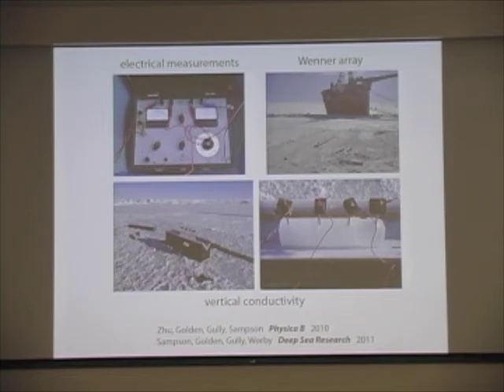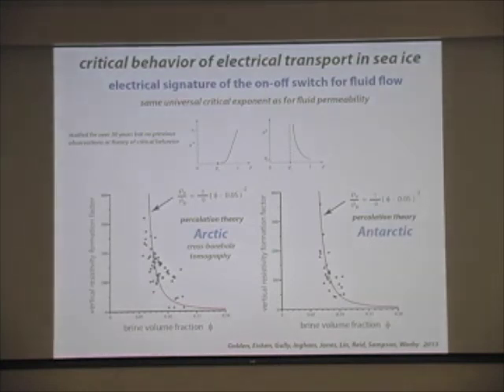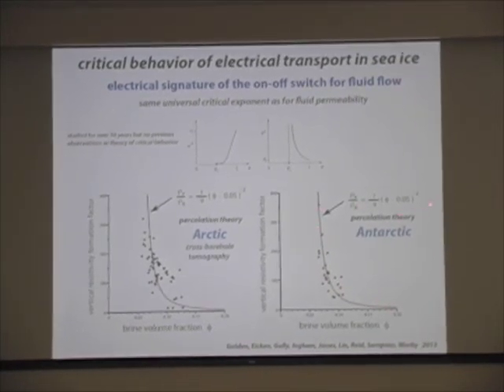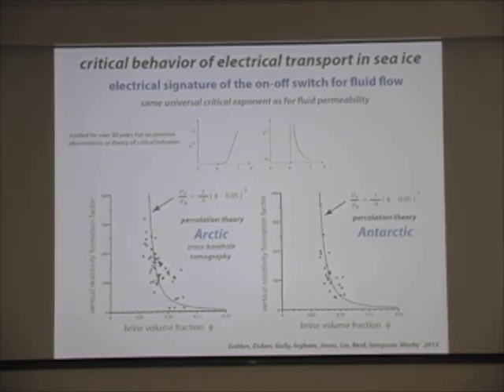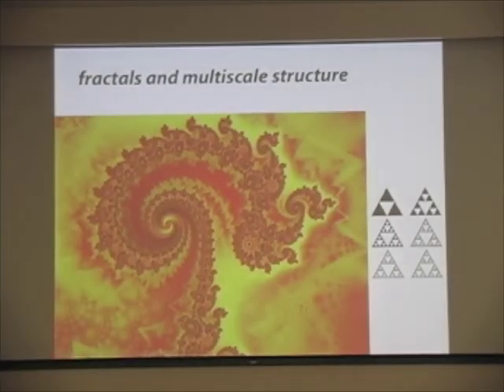All the previous ways of measuring the conductivity properties of sea ice, the vertical and the horizontal, were all mixed up. But we were interested in relating the vertical permeability to the electrical conductivity. So we extracted ice cores and then directly measured the vertical conductivity. And as a result, after people studying this for 50 years, we had the first measurements and theory of this on-off switch of my rule of fives. So in other words, here's data from the Antarctic, and this same beautiful theory that we developed for permeability of the ice.